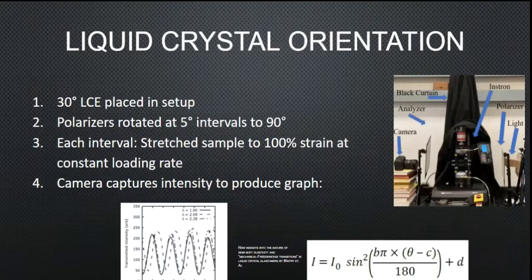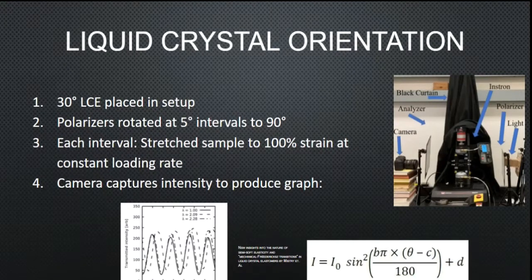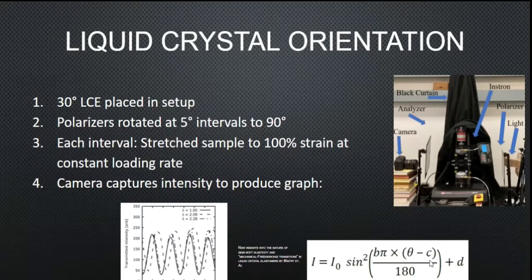For liquid crystal reorientation, we moved on to samples that weren't zero-degree LCEs — this one is a 30-degree LCE. If you remember, LCEs will polarize light in the direction of the liquid crystals, and polarized light will change its intensity. So if you put two polarizers on either side of the LCE and rotate them at five-degree intervals to 90 degrees, at each interval you stretch a sample to 100% strain at some loading rate. A camera captures the intensity to produce a graph with intensity on the y-axis and polarizer angle on the x-axis. This graph can be fit to an equation, and when the polarizer angle matches the liquid crystal angle, the intensity is minimized. By finding the parameter C in this equation, we obtain the liquid crystal angle.